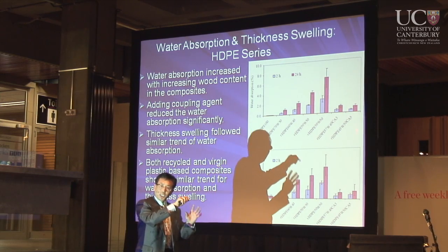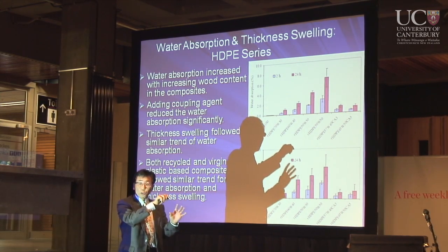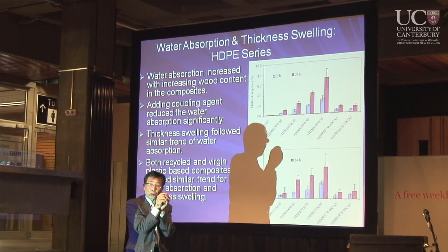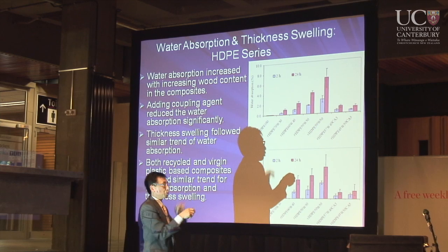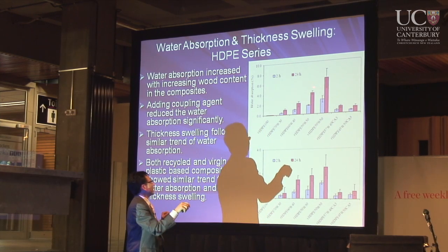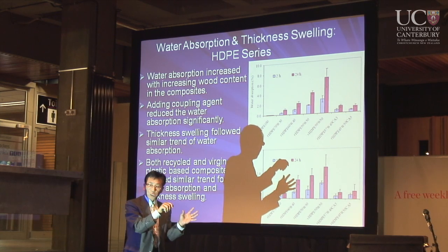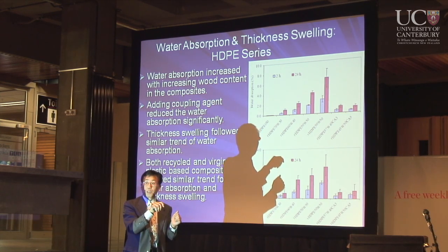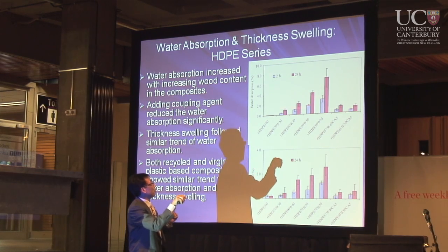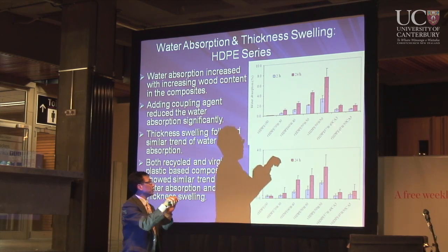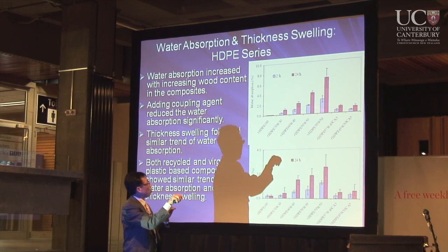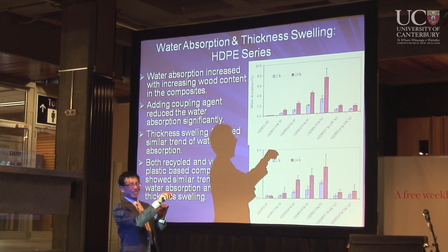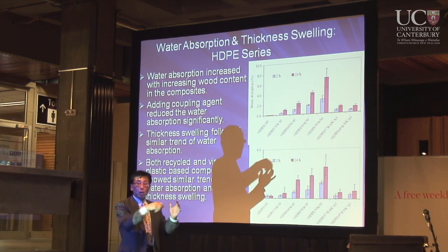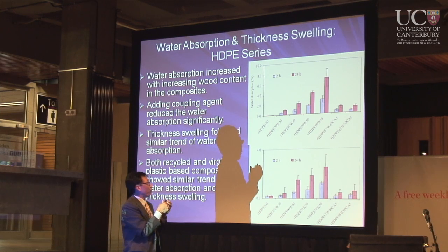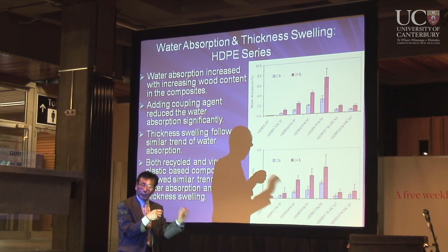However, this is much lower than wood. If you put a piece of wood in the water for 24 hours, the wood can absorb quite a lot of water, at least 30%. So that is a lot. But when we add a little bit of coupling agent, the water absorption is reduced quite significantly. That's no surprise, when you hold the material together very firmly and stop water penetration.